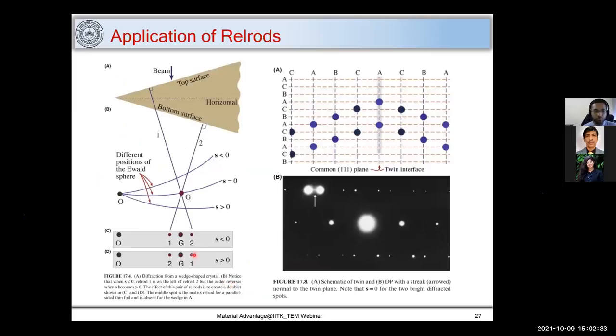Now, for the application of rel rods, you can see that the sample will not be flat, as we see, it will always be tapered. And you can see that the beam is interacting with the top surface and the bottom surface. And how does it form an image or diffraction spots? So this surface will create a diffraction spot here, and this surface will create a diffraction spot here. How is this useful?